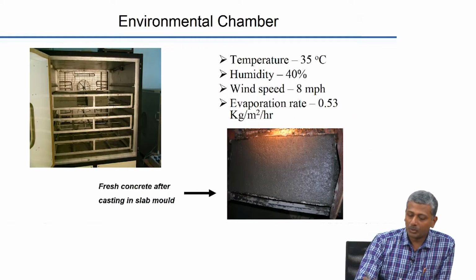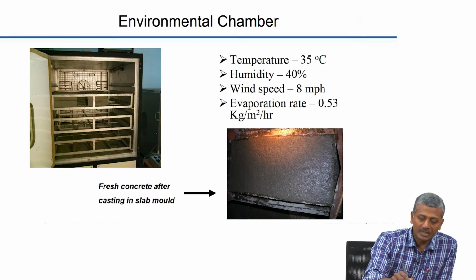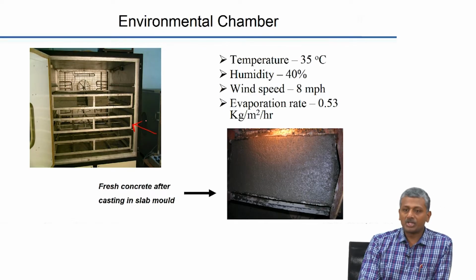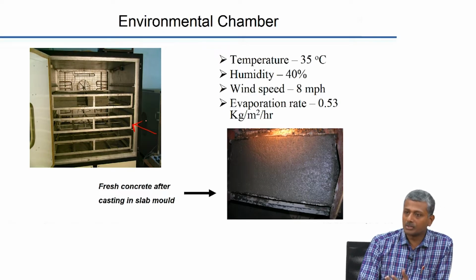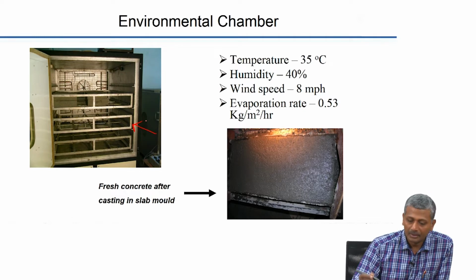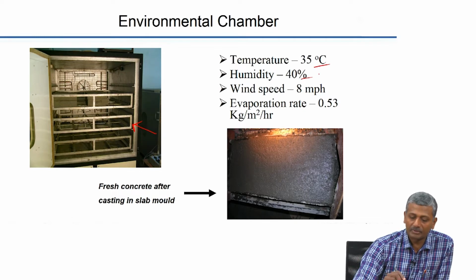Concrete was prepared and put into these molds, and these molds were then transferred to an environmental chamber, which is kept at a specific combination of temperature, humidity and wind speed. The temperature was 35, humidity was 40%, and the wind speed was maintained with the help of these fans that you see on the inside of the chamber, and that worked out to about 8 miles per hour.